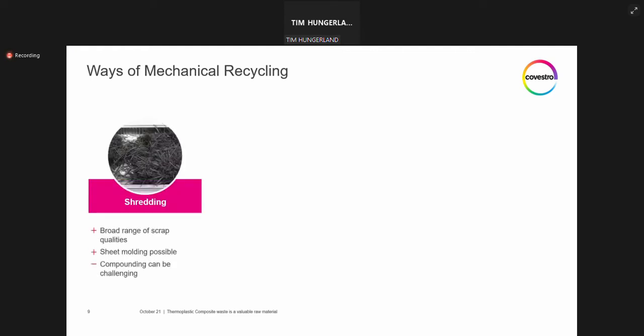Firstly, shredding is a common technique for size reduction of any sorts of solids. The advantage of this process is that a broad range of different scrap qualities can be handled. However, depending on a subsequent processing step, the technique can constitute certain limitations. For example, compression molding of the shredded composite into new sheets might be doable, even if the material is quite coarse and inhomogeneous. But on the other hand, for using the scrap as filler material in compounding, the size and the homogeneity of the scrap usually needs to be adjusted to match the specifications of the feeding equipment. This means that, for example, several subsequent shredding cycles or sieving steps might be necessary, which eventually reduces the overall efficiency.